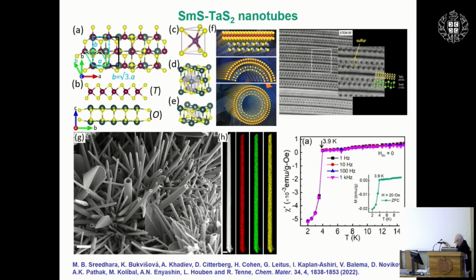So, as I mentioned, over the last 13 or 14 years we synthesized many such nanotubes, and some of them are superconducting. Especially we deliberated in recent years on the lanthanide or rare earth-based nanotubes, and you see they are superconducting at about 5 K, and this 1D superconductivity is very different from regular superconductivity.